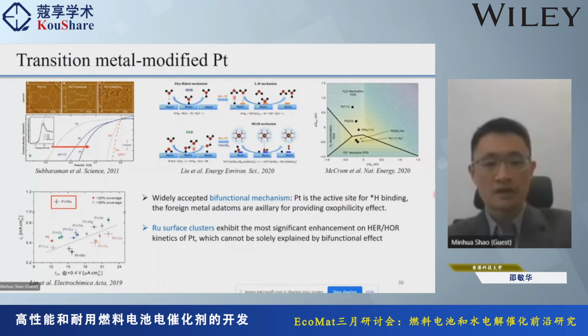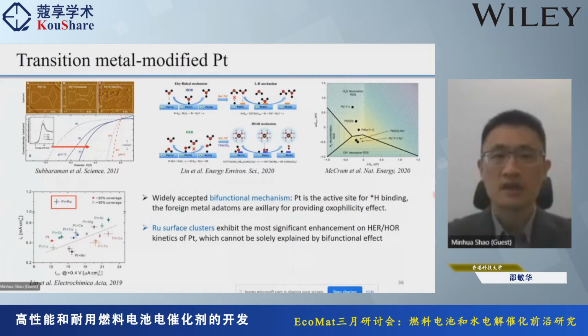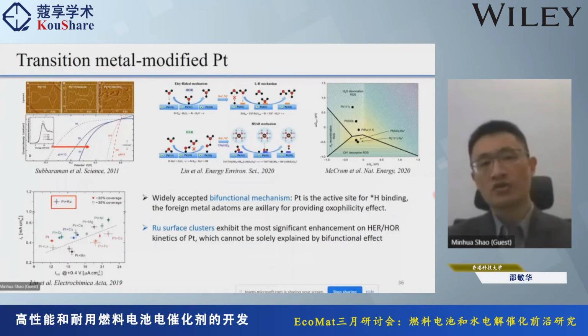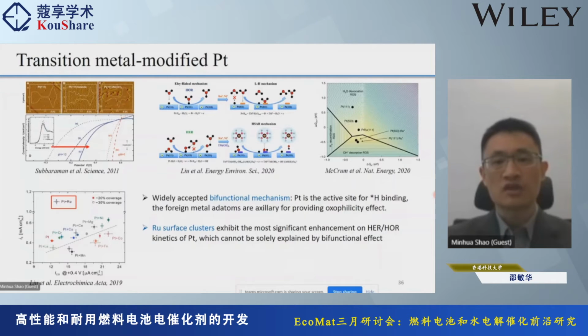All right. So lastly, I will maybe spend 2 minutes talking about the last topic. Platinum is very good for hydrogen oxidation and also hydrogen evolution, but in alkaline, the activity is much lower. Recently, it was found that by putting some transition metal like nickel or ruthenium on the surface, the activity can be enhanced. But the mechanism is not clear. The widely accepted bifunctional mechanism is that platinum is the active site for hydrogen binding, and a foreign metal like ruthenium provides oxophilicity, meaning it adsorbs oxygen-based species, and so promotes the hydrogen oxidation or hydrogen evolution reaction.